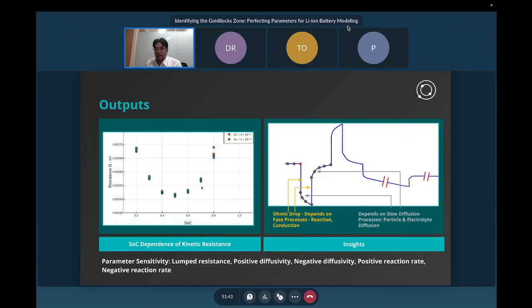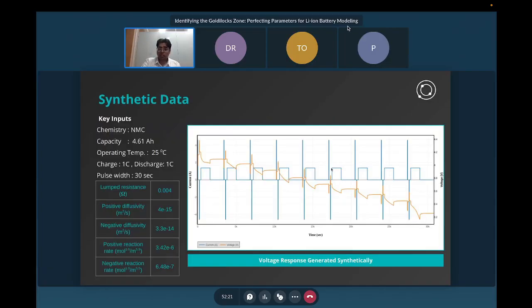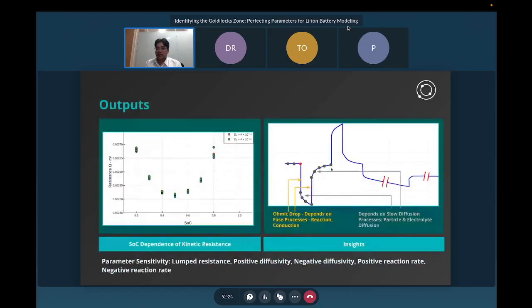Now, one of the important things I want to emphasize is that we need to also be aware of the sensitivity of these parameters on the different parts of the voltage curves. When I talked about this lump resistance and reaction rates, you know that this is the part of the voltage curve which is sensitive to the resistance and reaction, and this is the part which is sensitive to the diffusivity and reaction rates, and then you have a recovery which is solely dependent on the diffusion process. Now, because there are diffusion constants for anode and cathode, each of these might have a different kind of sensitivity, which I will talk about subsequently down the slides when it comes to uniquely identifying these parameters.